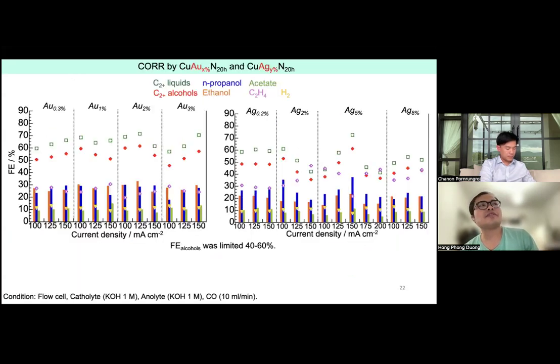And of course, the activity can be the most important thing as well. Firstly, we surveyed the samples with only one dopant, one metal dopant. We found that in any case, the efficiency for C2+ alcohol, including ethanol and propanol, was just around 60%, as shown here. And the lowest case was like 40%.